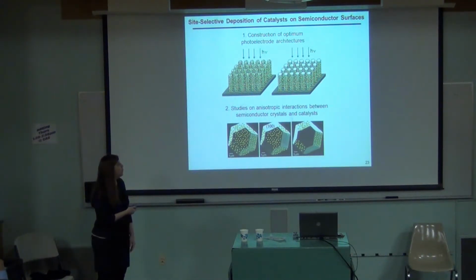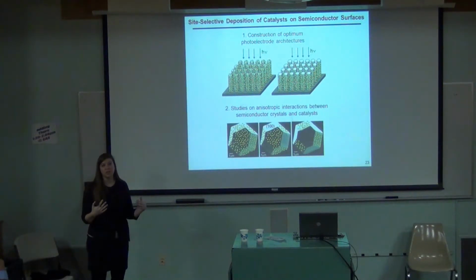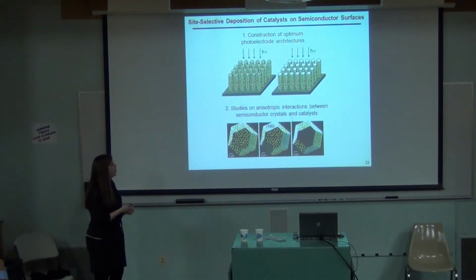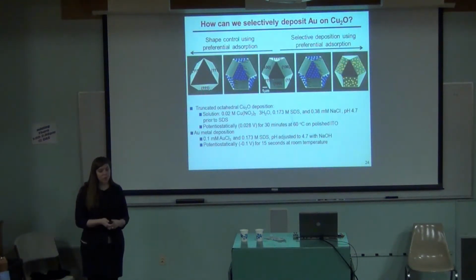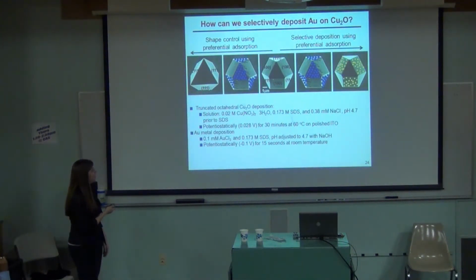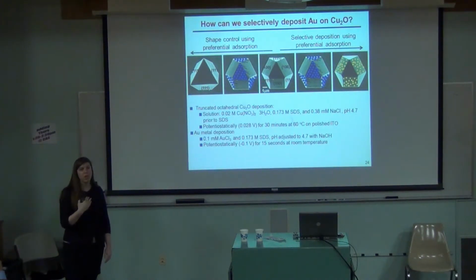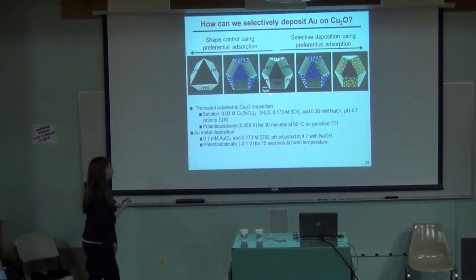So we thought, what if we did this with solutions? What if we could, since we can selectively adsorb something on a surface, what if that selective adsorption can actually block the deposition of something? And so we proposed that we could selectively deposit on the 111 and selectively deposit on the 100, and then we tested that out. So my part of the project was I wanted to see if we put SDS in solution and we have gold in the solution as well, can we electrodeposit gold just on one plane? Can we put it just on the 100?